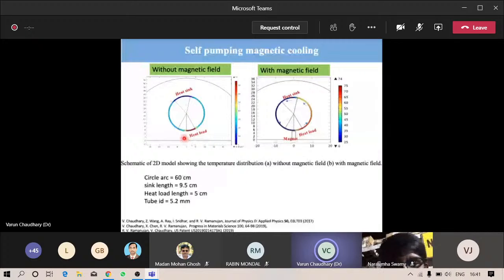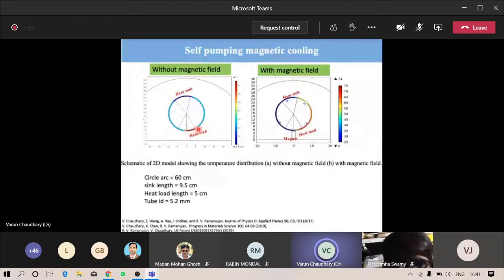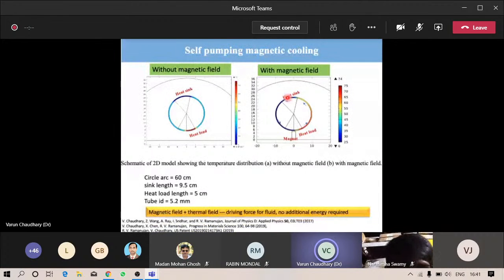These are the simulated results. The first window shows the heat load and heat sink without a magnetic field, and you can see that the heat is only at high temperature in this region and low temperature in this region. But when we apply the magnetic field, it starts to circulate and transfer heat from here to the heat sink. So the magnetic field plus the thermal field drive the ferrofluid and cool the system.